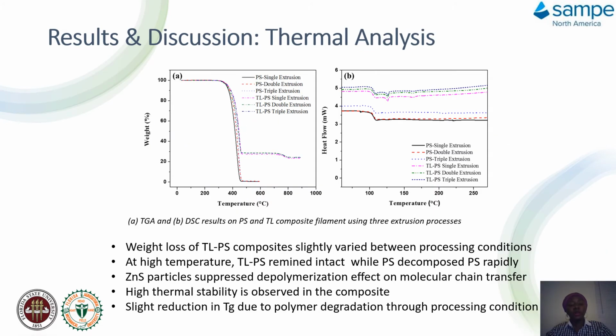So to further understand the thermal analysis of the composite, we compare polystyrene with the composite. We did polystyrene also for 3 processing extrusions, the same as we did for the composite extrusion. For polystyrene, we can see there is a continuous gradual weight loss in the polystyrene as well as for the composite.